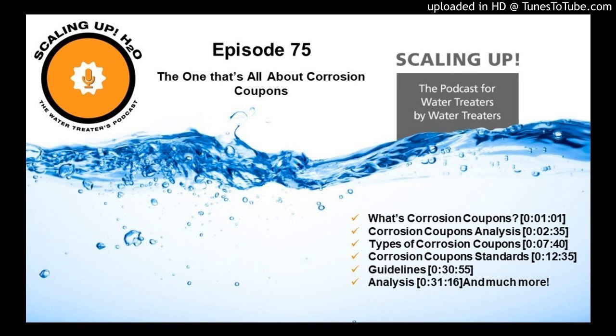Like I said, work with the manufacturer that you're getting a lot of your pumps and controllers from now. I am sure that they have corrosion coupon holders, but what they've done is manufacture these so you will get the same results as we were just referring to in the G4. So things that they're going to be doing is making sure that we have flow between 3 to 5 feet per second, and that we have a corrosion coupon rack that is attached from the